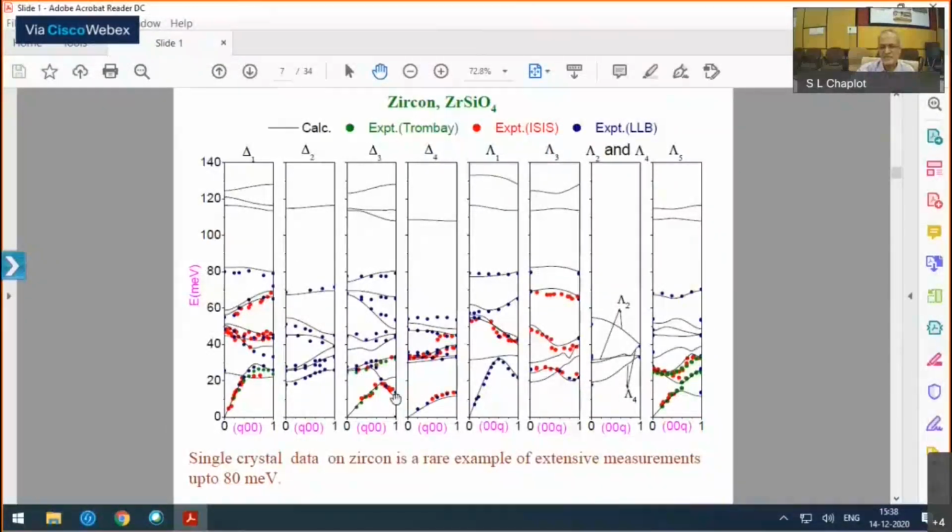But around phase transitions, these phonon frequencies change very significantly as a function of temperature or pressure, and its eigenvector is closely related to the nature of the phase transition, the way the atoms are displaced in going from one structure to the other. It particularly applies to second order phase transitions, but may be of interest to other transitions also, because it will signify how a given parent crystal structure becomes or tends to become unstable. So that is one way.